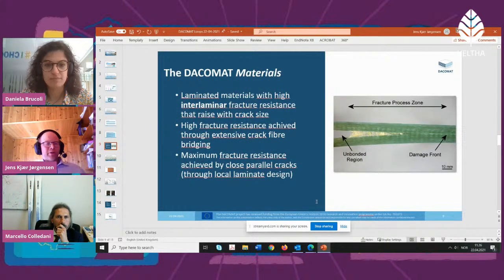So what is our approach to achieve this? First of all, we consider laminated composite materials, made from fabrics stacked and infused, and we consider interlaminar fracture resistance. So we have produced materials with a high interlaminar fracture resistance that rises with crack size. So when the crack size increases, the fracture resistance increases. And this we have achieved by making materials that have good properties with regard to generating so-called fiber bridging, which are fibers going from one fracture face to the other.